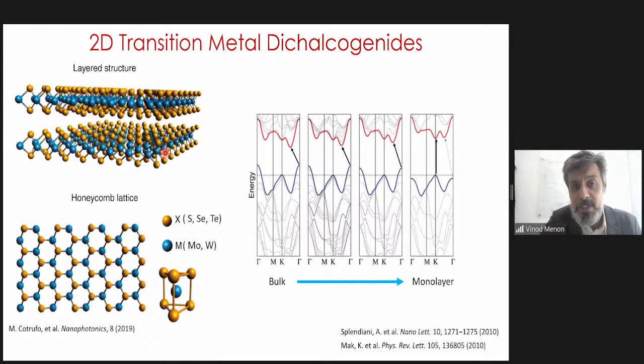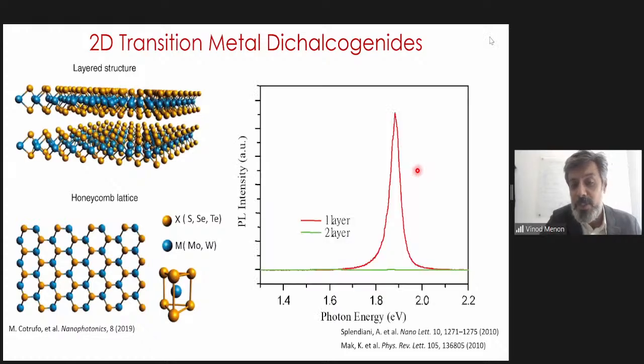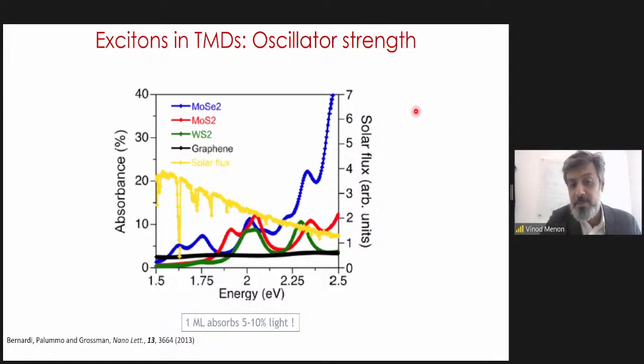What also happens in these materials is as you go from the bulk form to the monolayer form, you can go from something that is an indirect bandgap material to a direct bandgap material. And this makes it very interesting because if you think about the luminescence properties or the optical properties, just going from two layers to one layer shoots up the photoluminescence by about a factor of 1,000. So in the monolayer limit, you get a lot of intriguing properties.